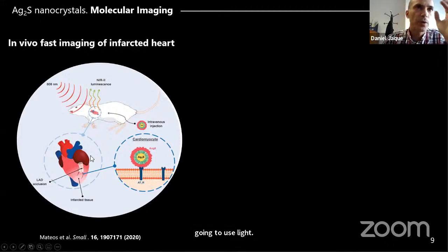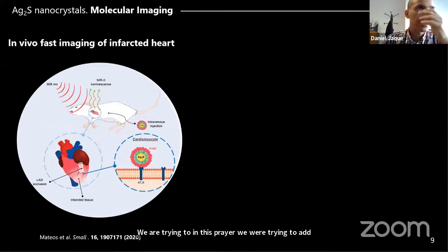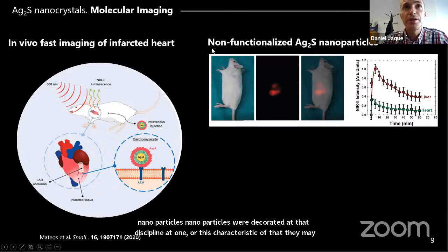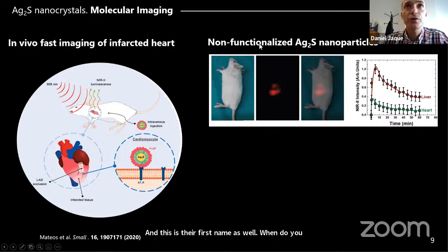In this project, we were trying to detect infarcted tissues in the myocardium. So we induce an infarct in the animal, and after the infarct, we inject the nanoparticles. The nanoparticles were decorated, attached to this AT1R that is characteristic of myocardium after infarct. And this is the fluorescent image we obtain. When you induce infarct, and then you inject non-functionalized nanoparticles, or nanoparticles without this antigen here, nanoparticles are accumulated in the liver and in the spleen, but not in the heart. Okay, there is no molecular accumulation or molecular imaging of the heart.